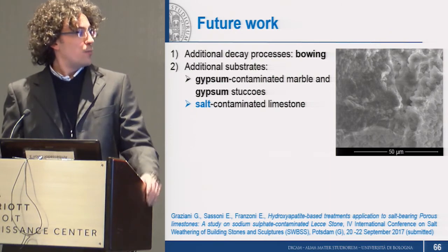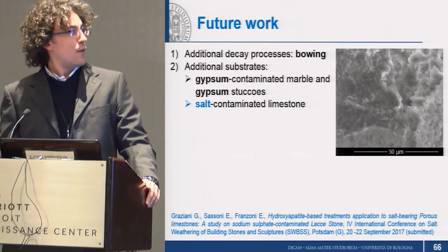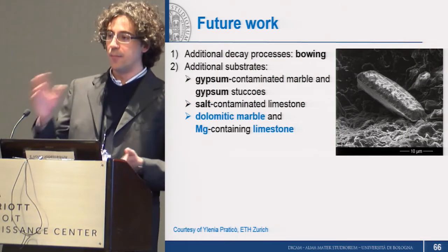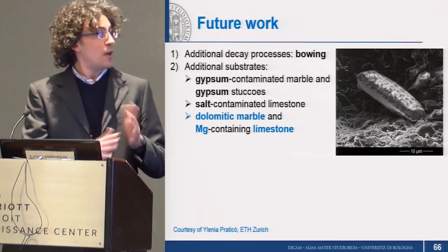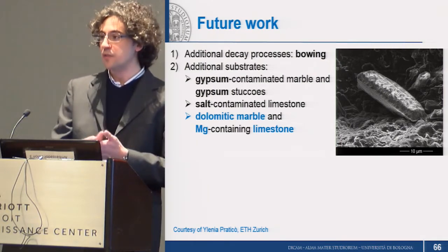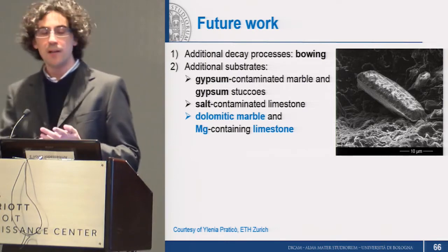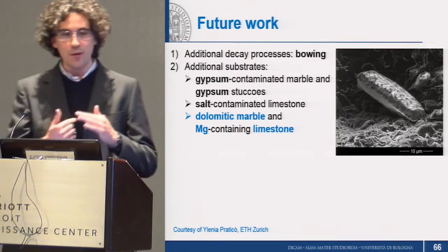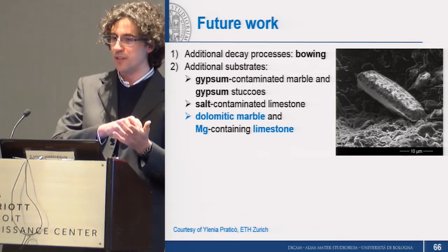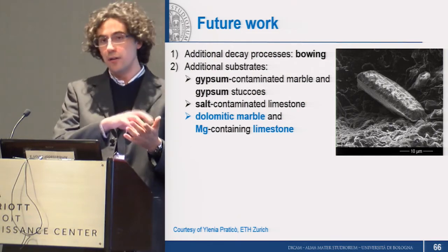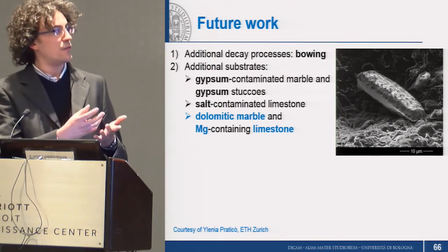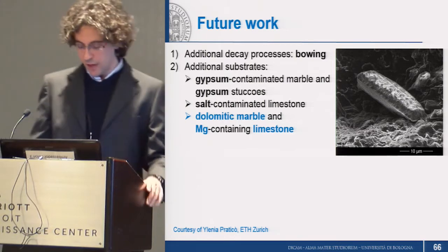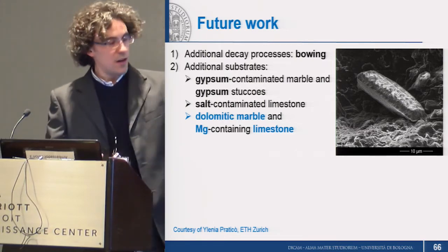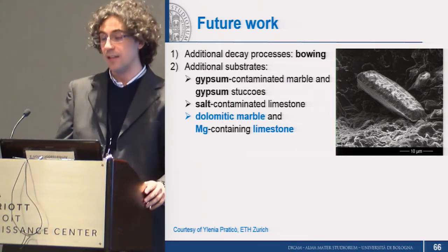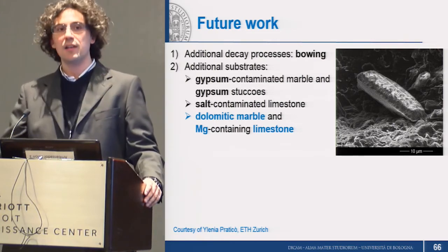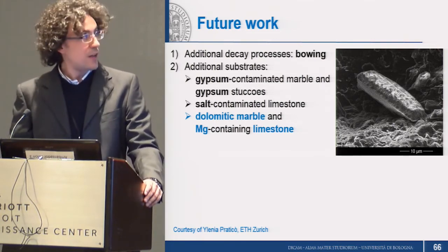So people at ETH in Zurich are now also investigating the effects of applying the treatment to dolomitic marble and magnesium-containing limestone. This is an important and tricky part because we found out at our own expense that when magnesium is present, not only or not mainly calcium phosphates form, but magnesium phosphate may form as well. As you can see, a very big crystal on the right. And this is a problem because this may prevent the consolidating calcium phosphates from forming.